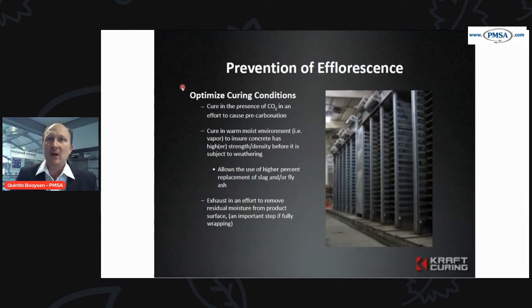Another method we are presenting today is around optimizing the curing conditions. So if you cure in the presence of carbon dioxide, which we are able to do through a burning system where we have a vapor system, we burn gas, and the gas forms carbon dioxide through the burning process, and you have this carbon dioxide floating inside your curing chamber. This is a typical curing chamber. That carbon dioxide will ultimately bond on the surface with the free lime or the calcium hydroxide, forming, just below the surface, because it'll penetrate, a calcium carbonate.